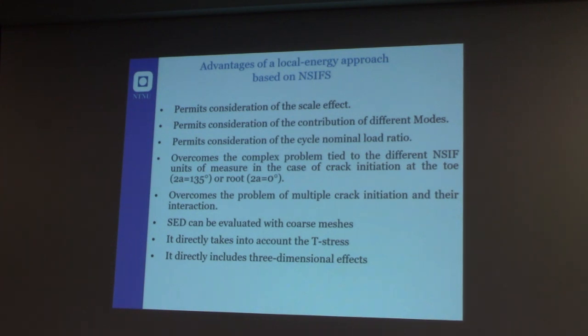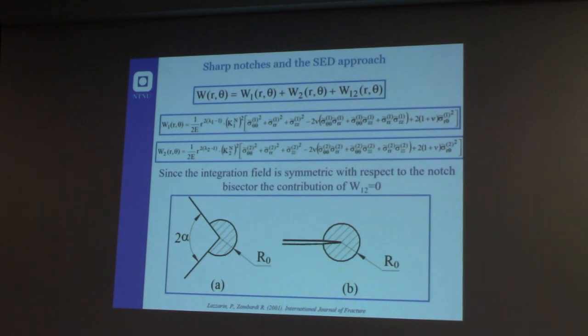So this makes the computational effort much higher because you cannot use a coarse mesh. You always have to use a very fine mesh close to the notch tip. And actually, what Lazzarini and Zappalorto did first in 2001, and after that we extended to many other applications, was to develop a kind of parameter that is called R0. It's reminiscent of the rho star value of Neuber, a kind of microstructural support length called rho star, and here is called rho 0.